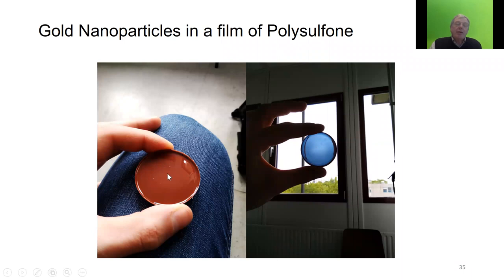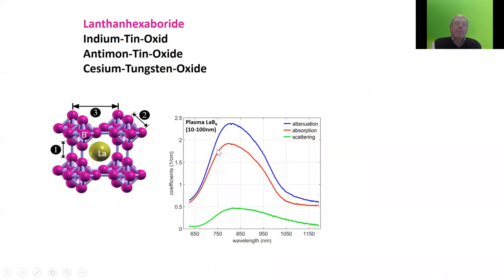You have a plastic film, and in this plastic film, you have, in this case, spheres. And you look at it in reflection, they shine, they appear red. And if you look at it in transmission, they are bluish in there. And this is because in transmission, you see the absorption, and in reflection, you see the scattered light mostly. You do not need to do this with gold nanorods. You might think they are expensive in there. You can do the same thing with a number of small particles from semiconductors.